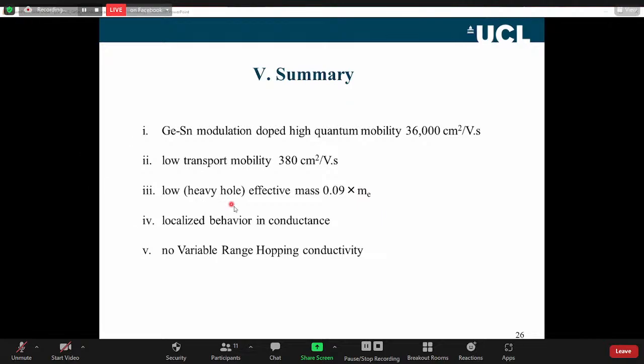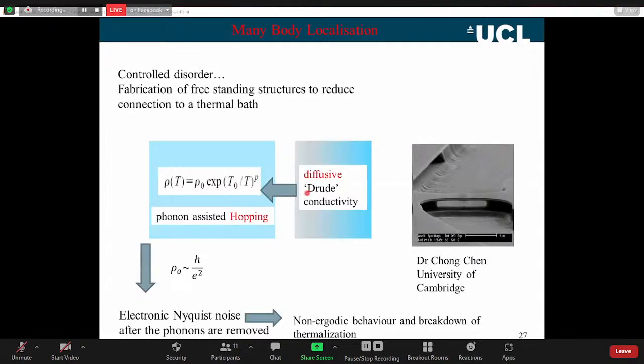We see this localized behavior in the conductance, and we don't see variable range hopping. It could be that if we were to measure the device at lower carrier densities, controllably at lower carrier densities, or at lower temperatures, we might see a variable range hop. And just to mention what we plan in the future with these materials is controlled disorder. If we're in control of the disorder, let's make use of that. Let's fabricate freestanding structures to take away the thermal bath.